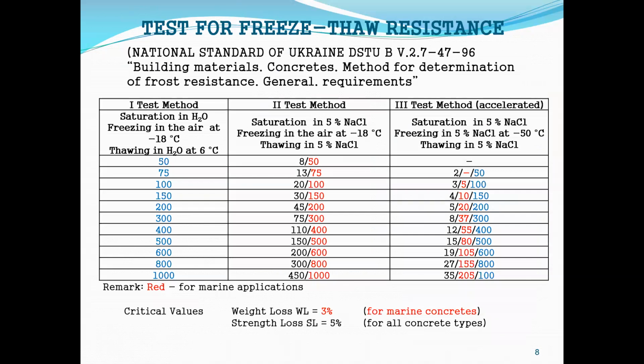A class of concrete in freeze-thaw resistance was designated as a number of alternate freezing and thawing at which a mean compressive strength decreased by no more than 5%. The freeze-thaw resistance of concrete was assessed by the correspondence between permissible number of freezing-thawing cycles by the mentioned method and by the first basic method prescribed in the mentioned standard.